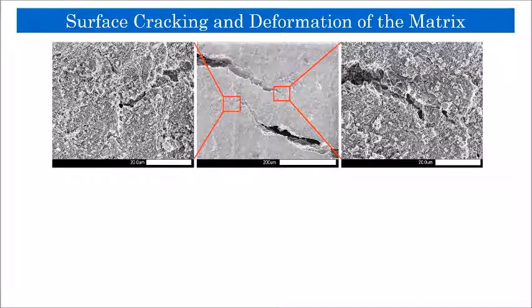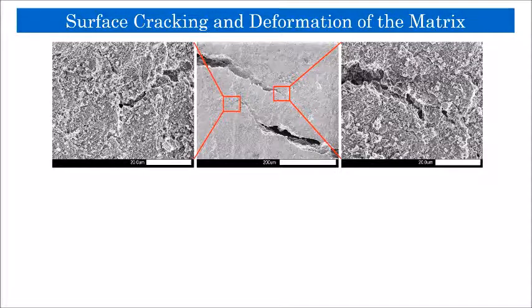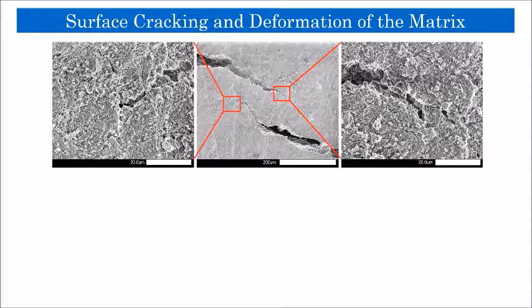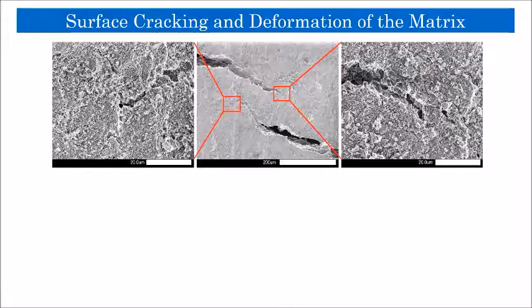The micrograph in the middle shows the growth of the crack on the surface as well as the case of bridging phenomena in that region. The other two micrographs magnified the branch-shaped tip of the crack at both ends.